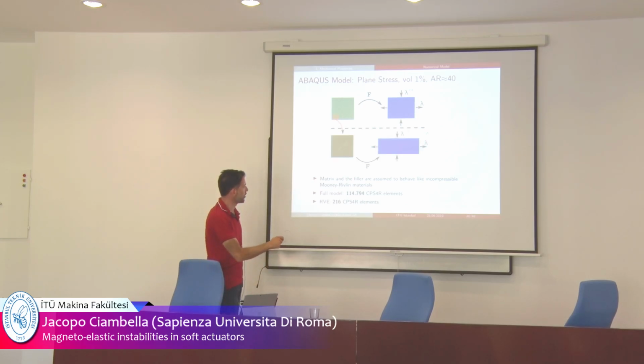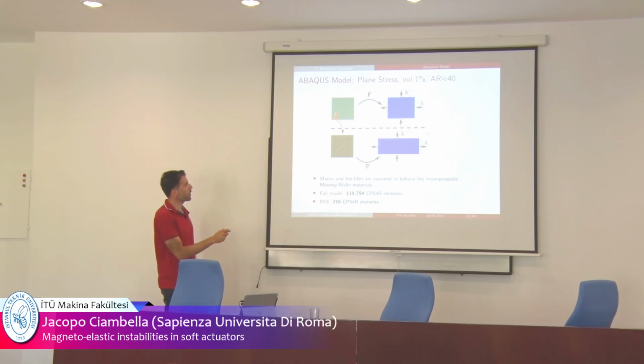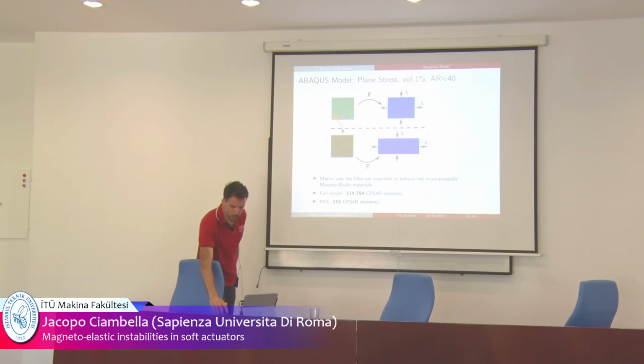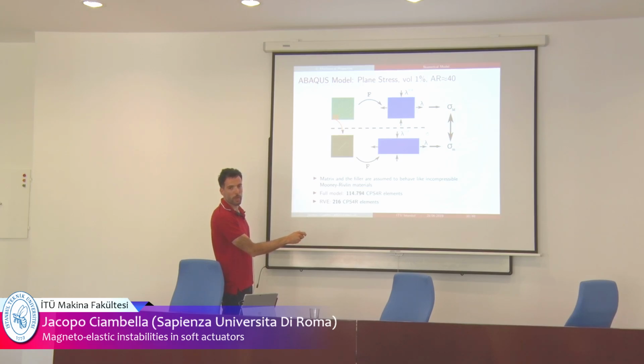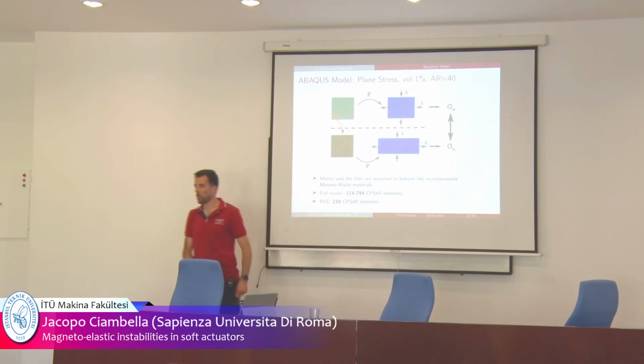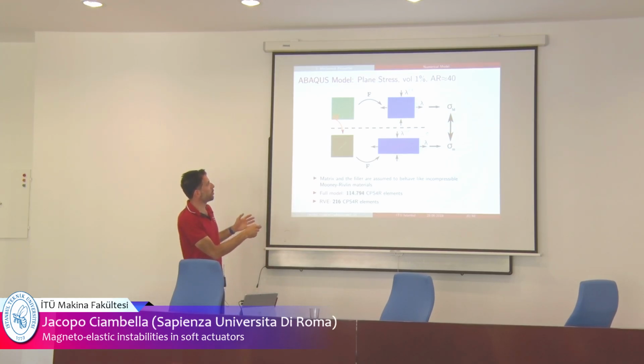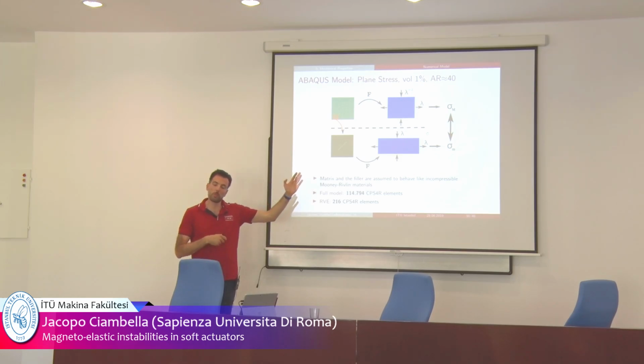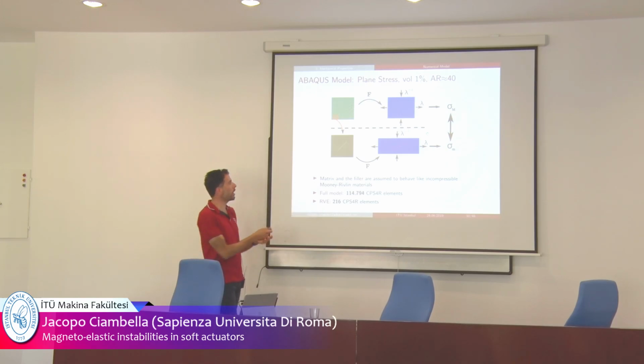The matrix was a Mooney-Rivlin material, and we also simulated a single fiber here, an RVE with a single fiber. The same thing: we apply the deformation and we have the stretch. We wanted to compare the macroscopic stress. For this you can use a standard transversely isotropic model, because you can think of it like a homogenized material. You have lots of fiber, all with the same orientation, so you end up with a transversely isotropic material with this being the axis of transverse isotropy.